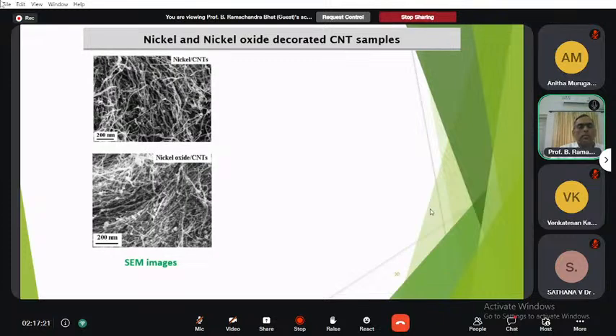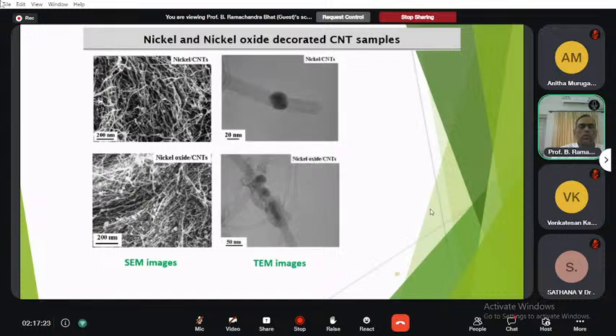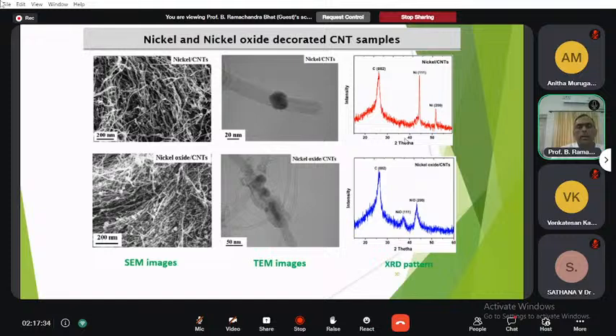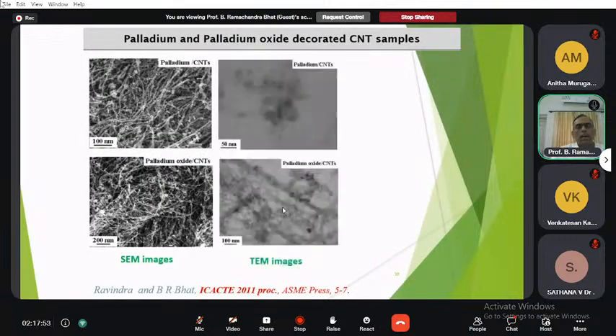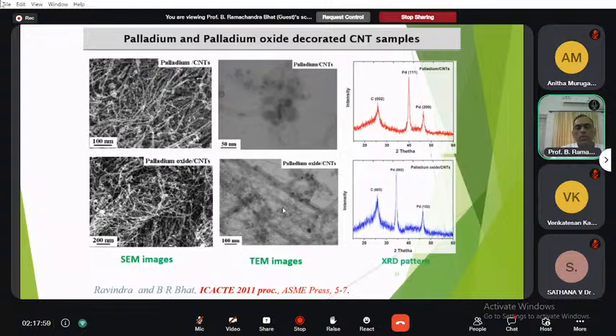You can see some images which show that the nickel and the nickel oxide are decorated on CNT, the SEM image as well as the TEM image. The TEM image clearly shows that the first one is a nickel metal nanoparticle, and this one is a nickel metal oxide. Nickel oxide decoration is seen. And we have prepared even the palladium as well as the palladium oxide decoration on the CNT.